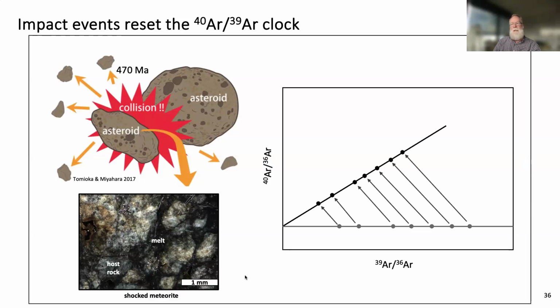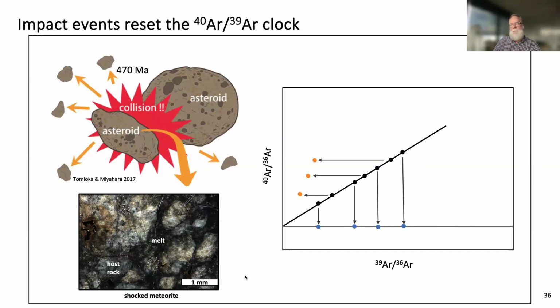isochron. But then the impact happens 470 million years ago, and two things happen. In the melt vein, we lose the potassium, but keep the argon. Outside of the melt vein, we lose the argon, but keep the potassium, or increase the potassium. So this process is this very rapid process happening during the quench of the melt veins. And this process is the gradual loss of the argon in the post-shock heated sample. So the sample remains hot for some time. The argon is able to diffuse out of the plagioclase and the mesostasis, and this is what we get.